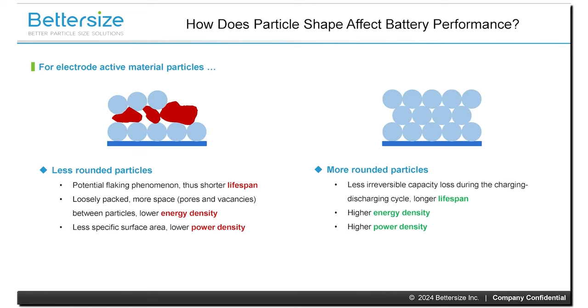Particle shape significantly influences the performance of lithium-ion batteries in several ways. In terms of the electrode packing density, different particle shapes affect how closely these particles can pack together in the electrode. Higher packing density, typically achieved with spherical particles, allows for more efficient use of space within the electrode. And this can lead to higher active material loading and thus higher energy density in the battery.